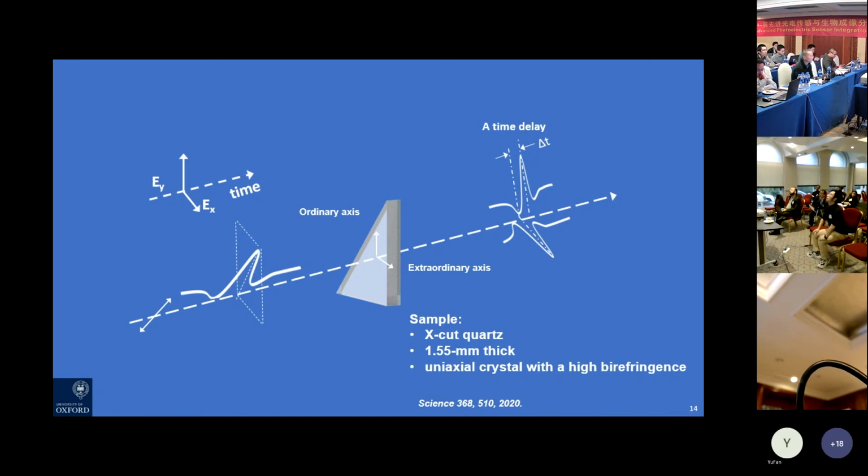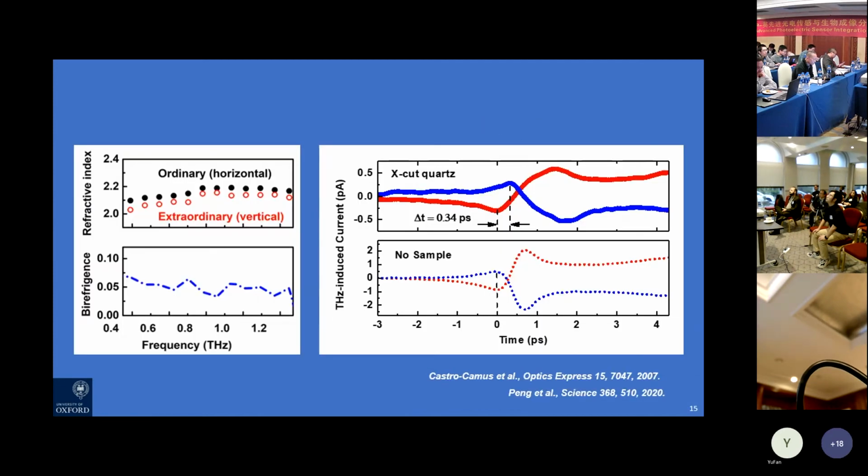It's an X-cut quartz. And with our 2-channel detector, we can directly measure the ordinary ray and the extraordinary ray in the system, and it is straightforward to extract the birefringence of this material, or to identify a birefringent material easily, with values consistent with the literature values.